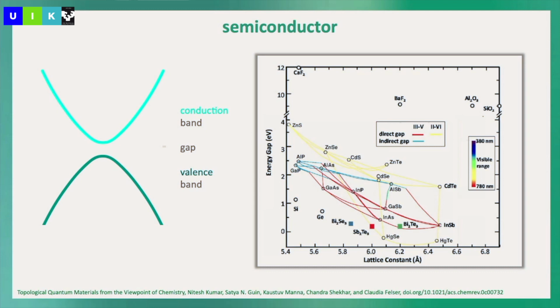And so if you go and look into binary semiconductors, you see here's the energy gap and the lattice constant, and this was known before even the paper of Charlie, so that you have these semiconductors where you can systematically see that the gap has something to do eventually with the lattice constant, because it has something to do with the bonding interaction and maybe other tuning parameters. But you see there's even a minus gap, so there's a negative gap. So this was already existing, that there were binary compounds which have an inverted band gap. So they are distinguished from the other compounds.